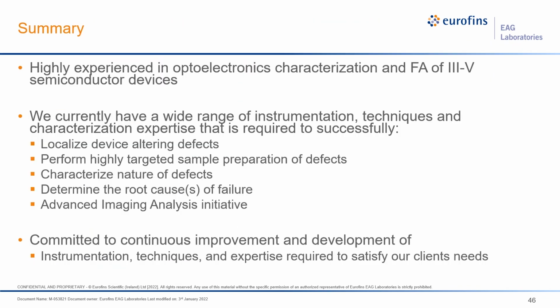So with that, I'm going to summarize the talk today and just say that EAG is very highly experienced in optoelectronics characterization and failure analysis of compound semiconductor devices. Myself, I've been doing this for almost 15 years here in North Carolina. We currently have a wide range of instrumentation techniques and characterization expertise that's required for the successful localization of device altering defects. We can perform very highly targeted sample prep with very low damage using focused ion beam. We can then characterize the nature of defects in the STEM or with CL, for instance, and use all these techniques to help determine the root cause of failure.